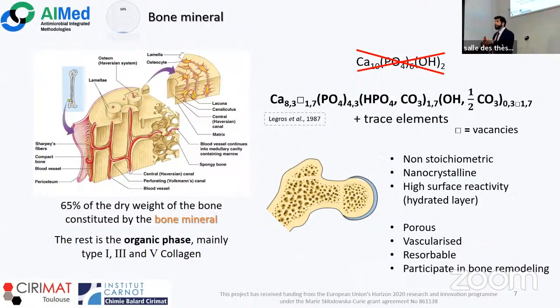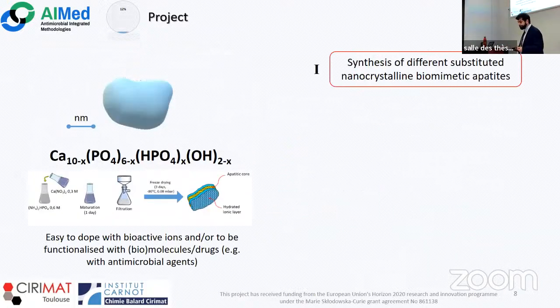And furthermore, when we increase the scale, the structure is highly porous and therefore vascularized. It is resorbable because of its high reactivity and the nanocrystalline shape of the crystals. And of course, because of everything that I just said, it participates in bone remodeling. So in our case, we decided to focus on the particular non-carbonated sub-stoichiometric nanocrystalline apatite.